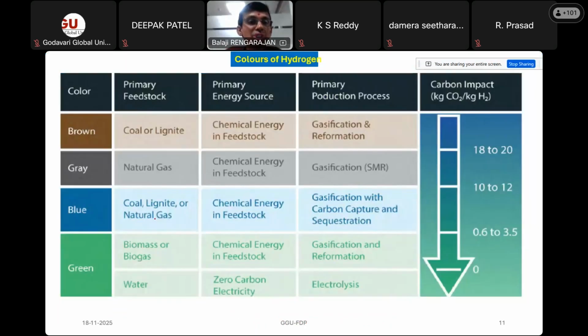So depending upon the feedstock and the amount of carbon dioxide emission while producing hydrogen, it is widely categorized as brown, gray, blue, and green. So brown is the coal gasification, because you do the gasification of coal along with steam, and then you get CO2 and hydrogen. But the emission of CO2 in this case is slightly higher, about 18 to 20 kg per kg of hydrogen. Whereas in the case of natural gas, because it's methane, a one carbon hydrocarbon, the amount of carbon dioxide emission is slightly lower than the coal based route. It is about 10 to 12, that is gray.